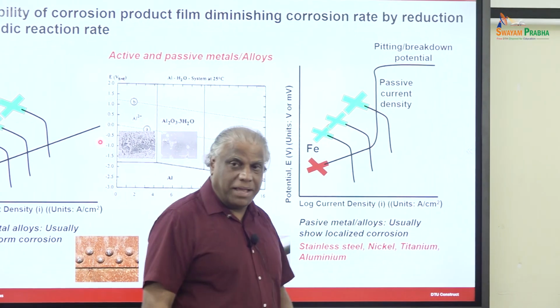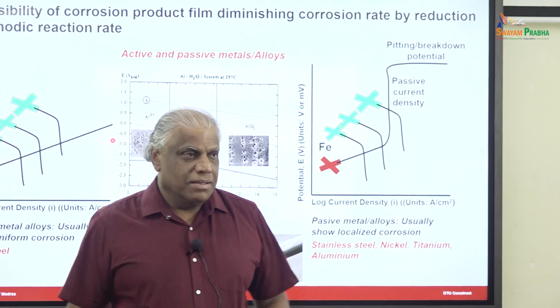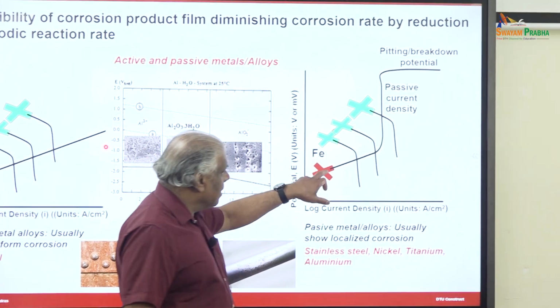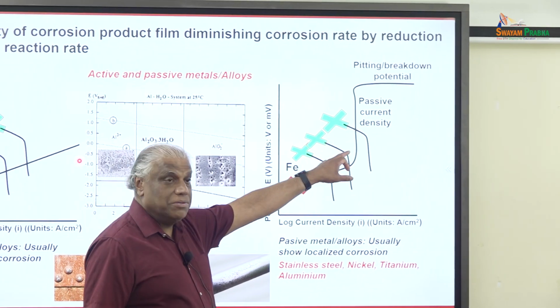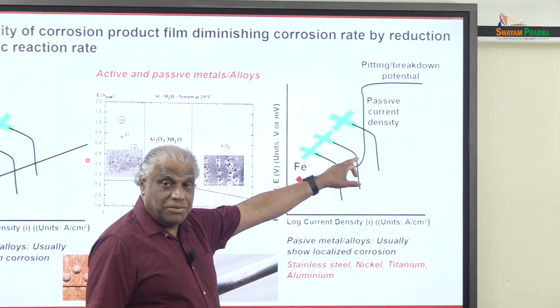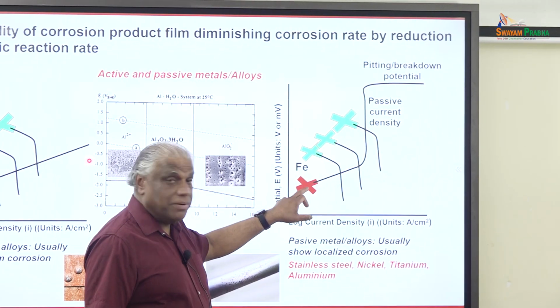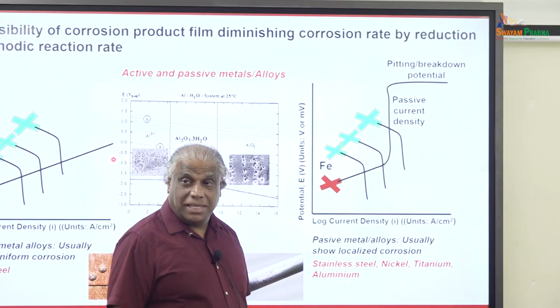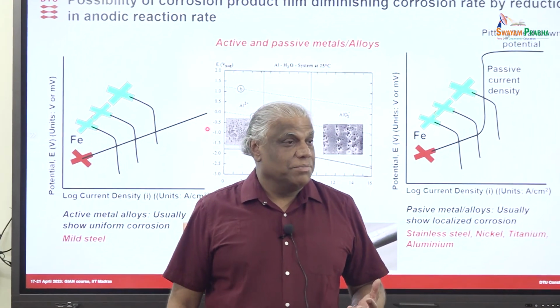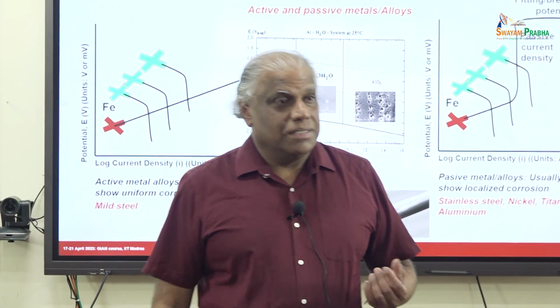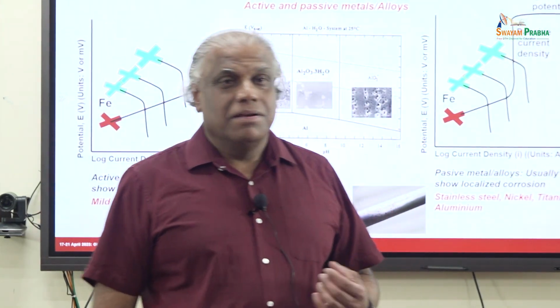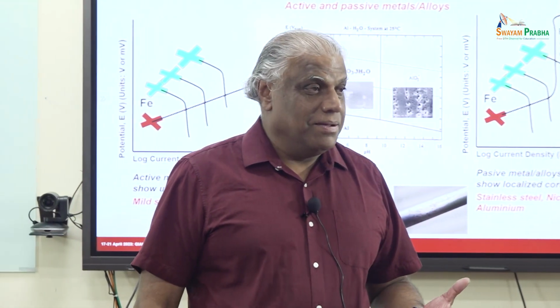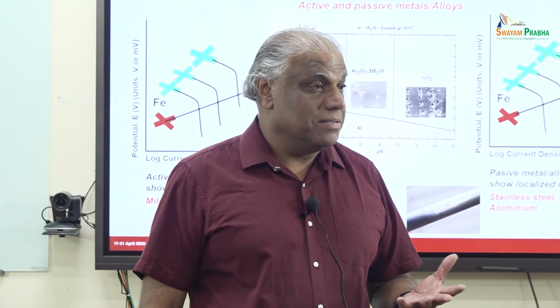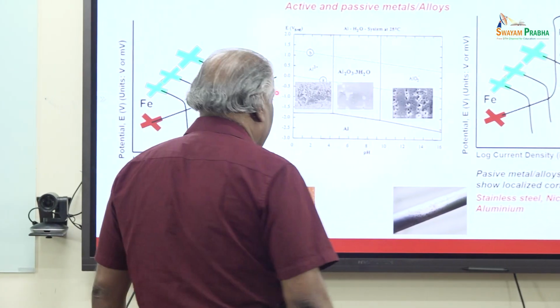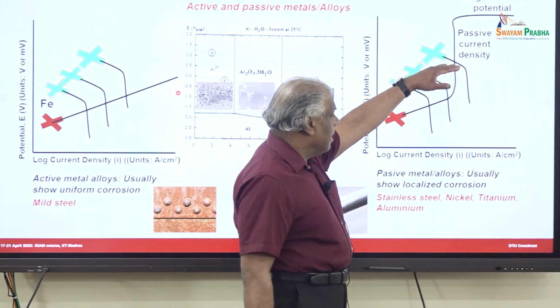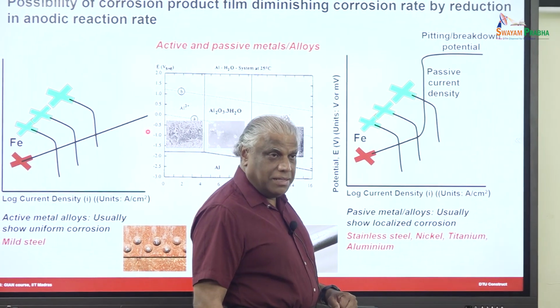That means that if you are using a passive metal, basically at the OCP condition you are here, you are not in the passive state, right? You agree with that? You are not in the passive state, you are here, but you need to put it in the passive state, and it is very easy to do that, because either you change the oxygen concentration in the solution, which might be difficult, or you add an oxidizing agent, and this is what we call oxidizing inhibitors. So you can add an oxidizing agent, and that way you can shift the potential to the passive region, and then you can get the stability.